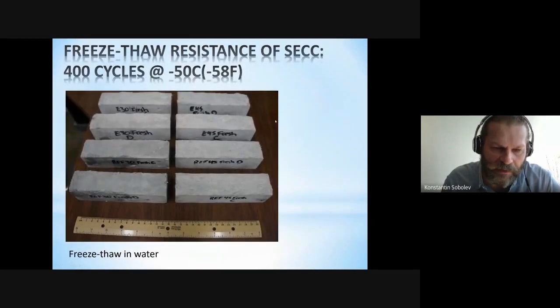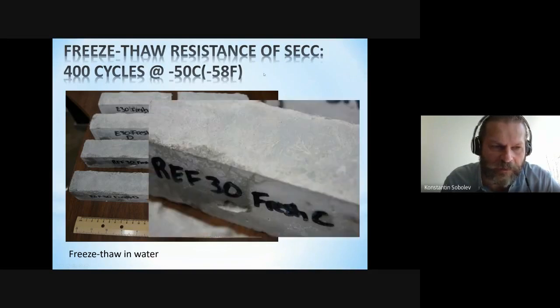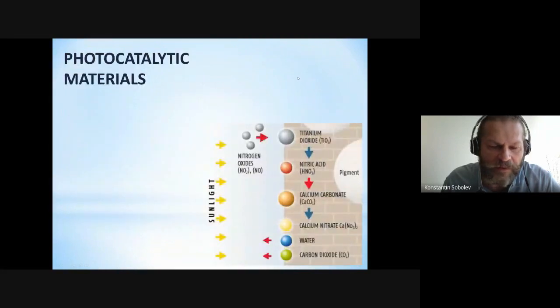Again, when we tested this concrete for freezing and thawing, we did 400 cycles at -50 C, which is an extremely harsh testing temperature. We demonstrated that performance can be considerably improved in terms of freeze-thaw and salt scaling. Well, I would like to briefly touch on photocatalytic materials. I need another maybe 2 minutes.